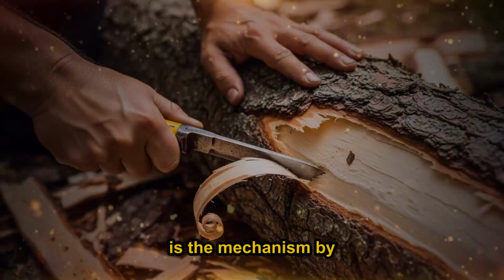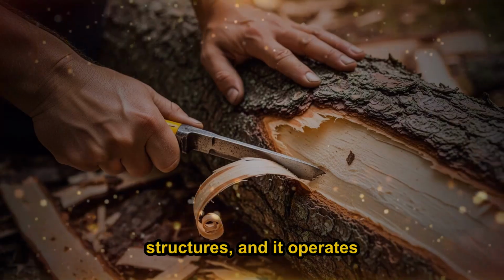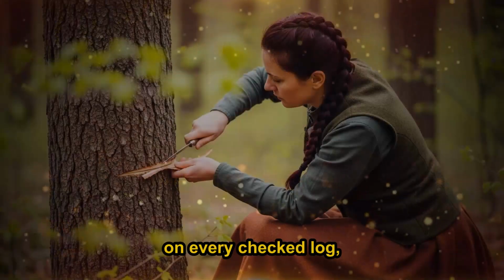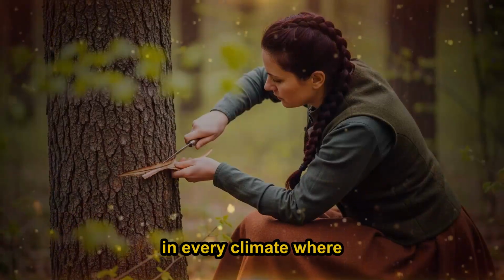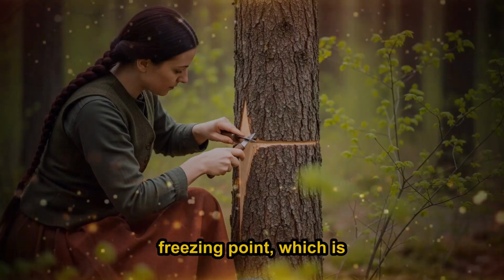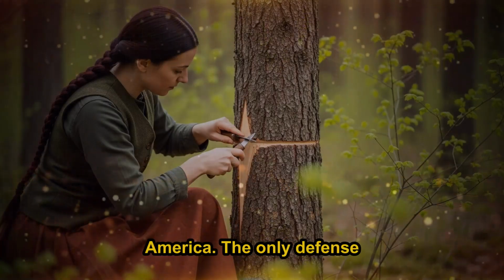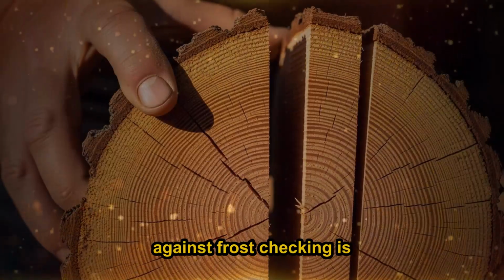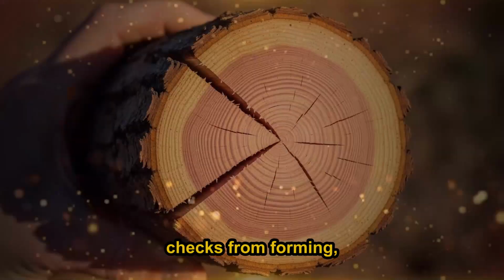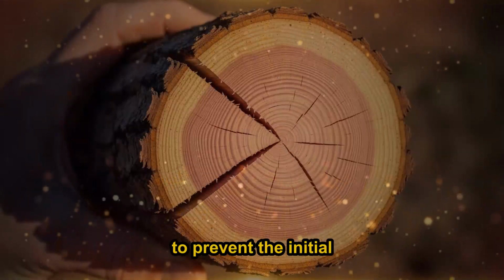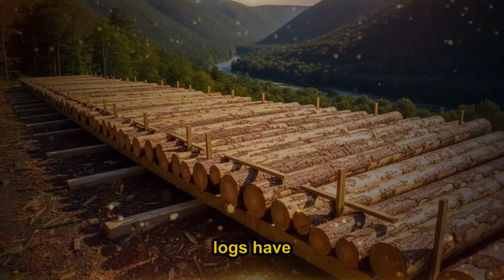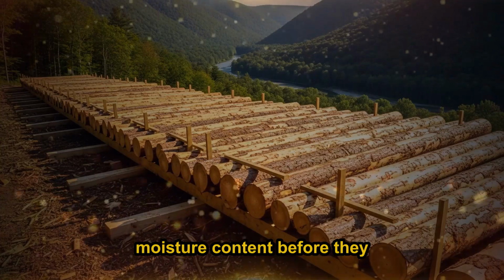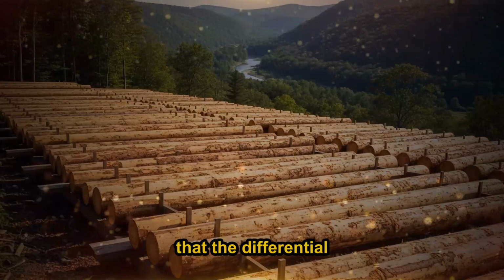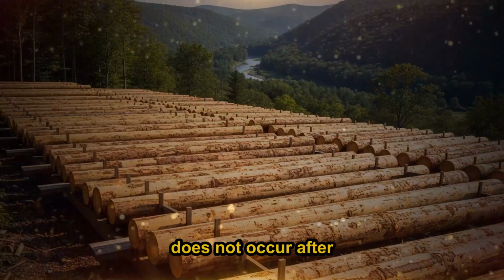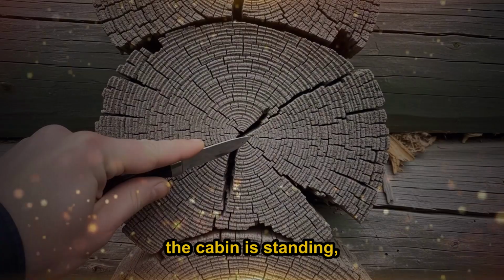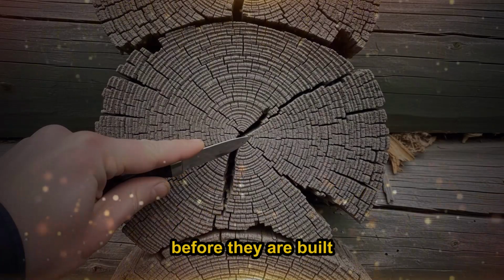This is the mechanism by which frost destroys wooden structures, and it operates on every checked log, in every cabin, in every climate where winter temperatures cross the freezing point, which is to say most of North America. The only defense against frost checking is to prevent the initial checks from forming. And the only way to prevent the initial checks from forming is to ensure that the logs have already reached their stable moisture content before they are built with, so that the differential drying that causes checks does not occur after the cabin is standing, unless the logs are seasoned before they are built with.